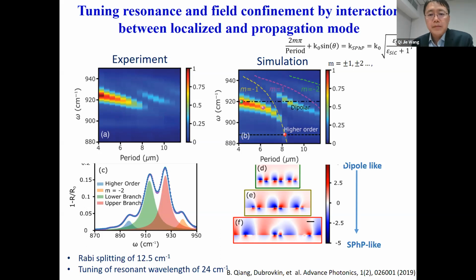Okay, at the same time, through such coupling, we can also tune the properties of surface Phonon-Polaritons in terms of resonance wavelengths, which can really cover over 24 inverse centimeter. By the way, the top left is the experimental result. And we also observe, we believe for the first time, the coupling of this dipolar mode with a higher order surface phonon propagation mode. Although it's relatively weak, indeed this is a mode here, which is also observed in the simulation. Okay.